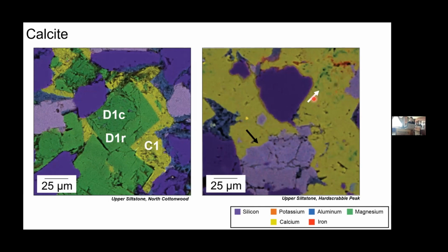So up here where this white arrow is, you can see some of these remnant areas of green, representing that dolomite was replaced by calcite, and there's still a remnant of that previous dolomite here. Then down here to the left with the black arrow, you can see the calcite cement is replacing this detrital feldspar grain, with a couple of little remnants of feldspar still present in the calcite. So again, type 1 is a pore-filling phase, type 2 is a replacive phase.